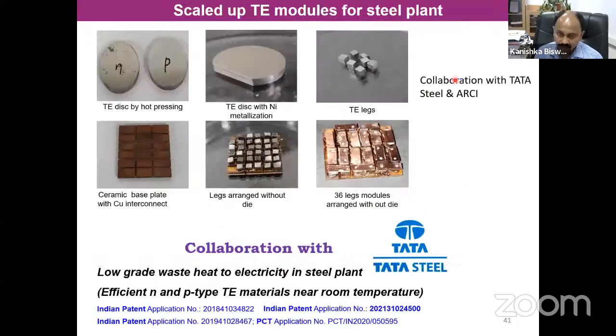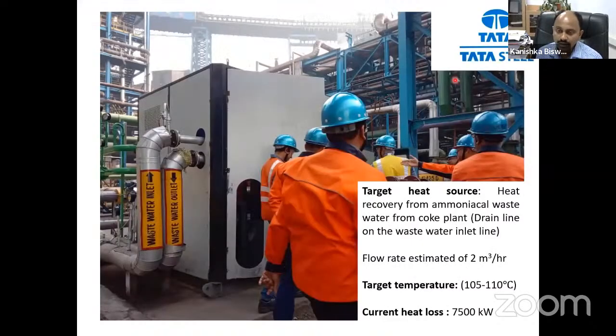So with this, we have collaborated with Tata Steel for the last 4 years, because Tata Steel contacted us. In a steel power plant, there are several sources of waste heat, and they contacted us based on our 4 patents on bismuth, antimony, tellurium, selenium material, because they wanted to convert the waste heat in the range of 105 to 110 degrees centigrade, not a very high temperature. So this is a photograph from their steel power plant.